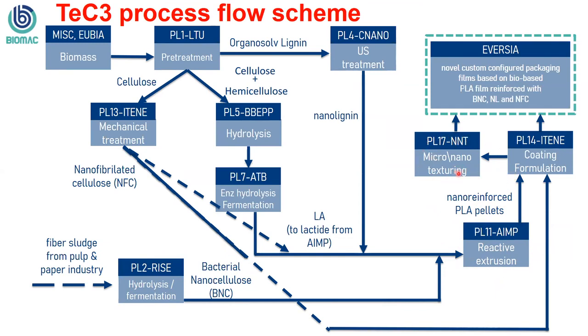And this formulation is then used as a basis for producing the packaging films that then can be directly micro or nanotextured, or you can also apply a coating to them. And so this coating can be directly based on nanofibrillated cellulose and give still more features as a means of changing the barrier properties, changing the surface characteristics of this multi-layer biodegradable packaging. And of course, as mentioned, the micro and nano texturing is what's getting us the self-cleaning characteristics, the antimicrobial characteristics that were noted previously.